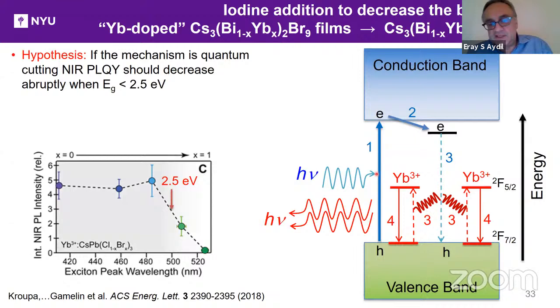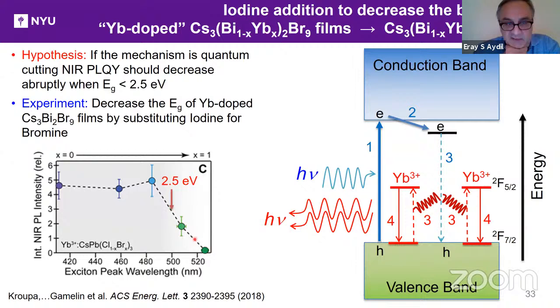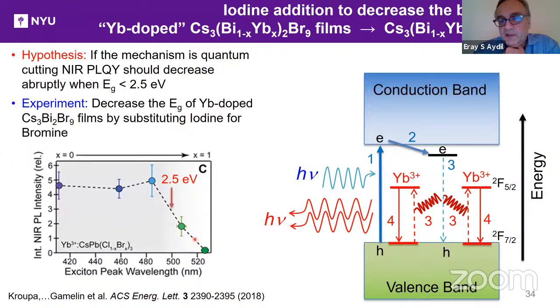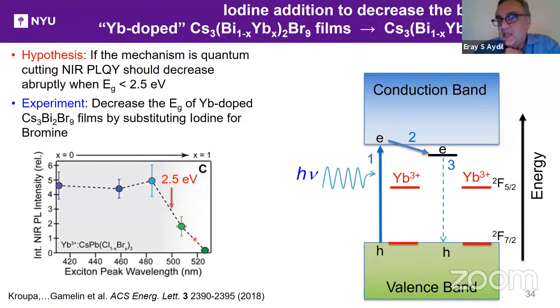So this is data from Gamelin's group, where they did the same thing, except they were working with cesium lead chloride and they added bromide to shift the band gap. And when the band gap fell below 2.5 eV, the photoluminescence intensity went to very low and zero. So then the idea is that you reduce the band gap to see if the near IR PLQY goes to zero. Okay, so that's the experiment that we're going to do. We're going to shift the band gap by substituting iodine for bromine. So the conduction band gap is going to come down. As a result, you can't excite the ytterbium and the near IR emission stops.